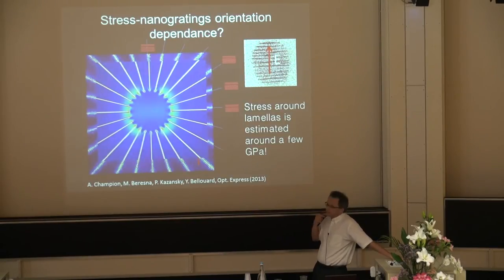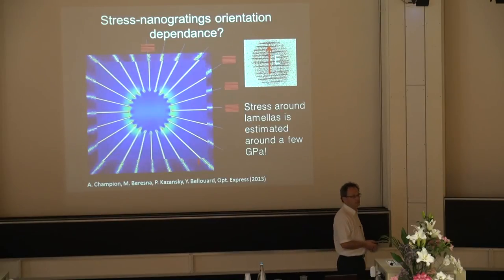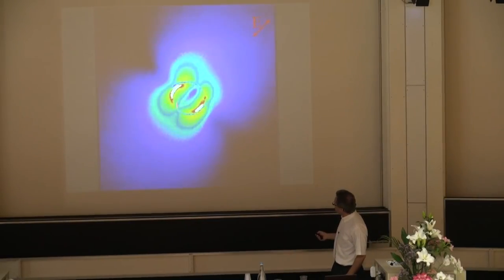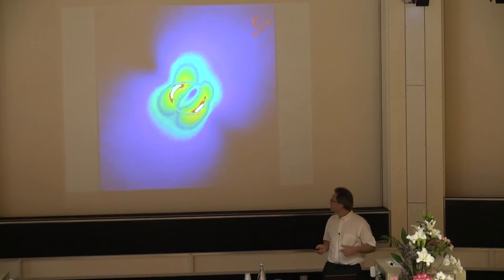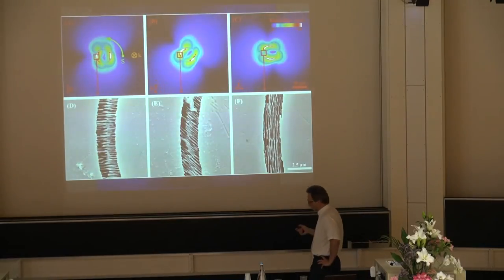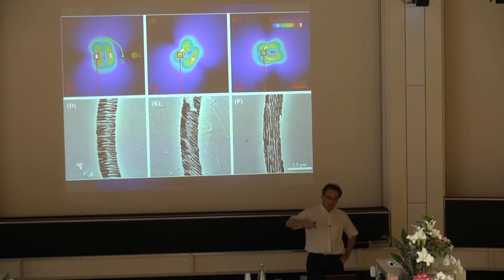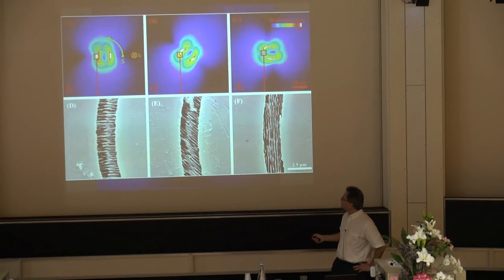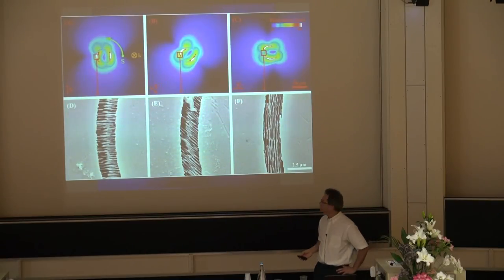And then, which is fascinating, when we did these experiments and looked at the possible stress we induced in the material, it's huge. It's several gigapascals. And you can play around, like for instance here, this is a homogeneous tube. These images you see here are what are called photoelastic images. So you look at the stress inside the material, how it developed, and you see that when you turn the polarization of the electric field, you change the stress orientation. So it's really a way to write different stress states, and that can be correlated to the nanostructure inside the modified zones.